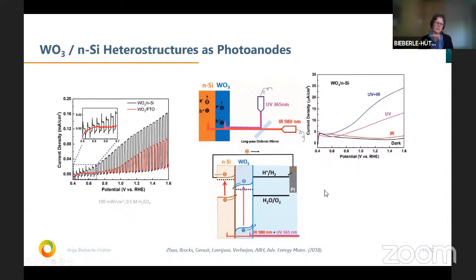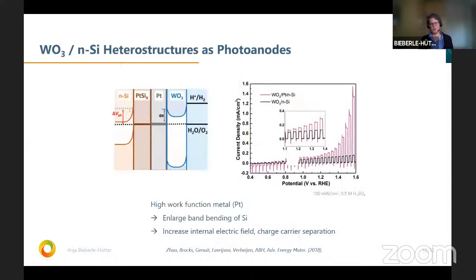And mainly what we find is that we have also an active contribution of the silicon, and it's not only the Z scheme that we get an increased performance. And what we did then is we added a platinum layer in between to increase the work function and to enlarge actually the band bending of the silicon, and could even increase the performance even more.